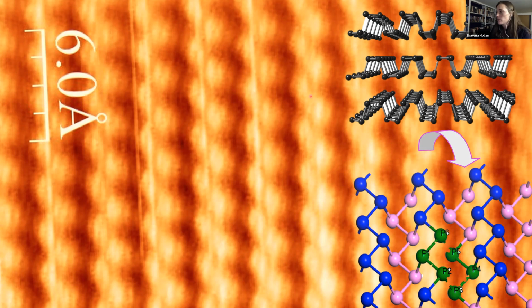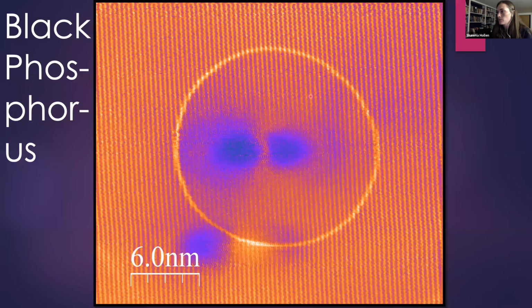Now, really interestingly, what happens, like if you take this one atom, for example, and if you took it out of the lattice, sometimes this happens. Sometimes there are missing atoms. It's a defect. In black phosphorus, if you have a missing atom, you get this enormous electronic signature. It's got this big dumbbell shape that spans 20 rows of atoms. And then there's this cool ring that shows up in STM images. And that's sort of a detail of the STM tip interacting with the semiconductor bands in the material, but it still shows the really large electronic effect in this material from just one missing atom.